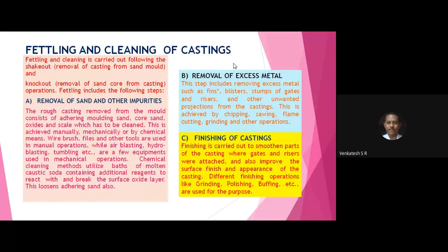After removing the casting from the mold box, some sand particles stick to the surface of the castings. These are removed by using a wire brush or a shot blasting machine or sand blasting machine. There will be a container or a chamber, looks like a boiler. In that there will be a circular table which rotates inside the chamber. All the castings are placed inside the rotating table of the shot blasting machine.